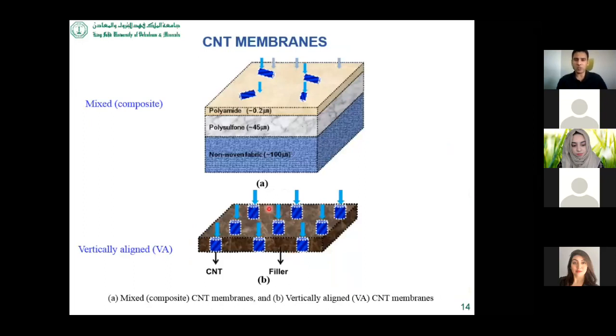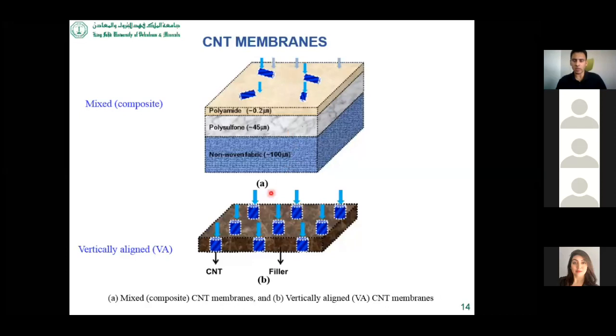Besides adsorption, another application is the use of CNT in membranes. It can be applied as a filler material in the membrane. This is a polymeric membrane or mixed matrix membrane. If you add carbon nanotubes here, various studies demonstrated that after addition of the carbon nanotubes, the characteristics of the membrane are improved. We normally get high flux, the hydrophilicity is increased, and the membrane gives high salt removal, antibacterial or anti-fouling characteristics. In this case, the CNT is randomly dispersed in the polymeric membrane, while in this case, the carbon nanotubes can be vertically aligned in the polymeric membrane. Of course, both of these have their own characteristics, and I will discuss both of these techniques in a little more detail in the coming slides.